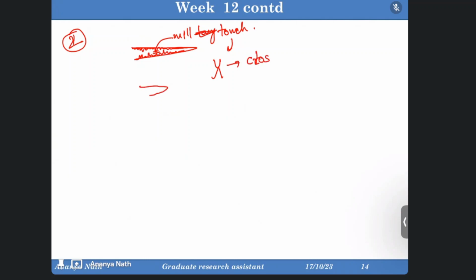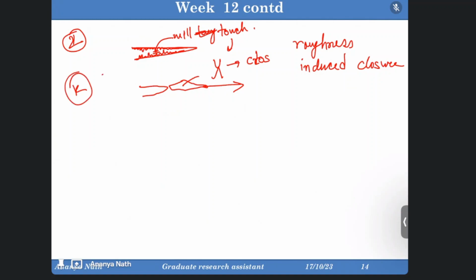So there will be two portions in the crack now, like this. There can be some void, or this void can again propagate and form a crack. So these things can happen, which is known as the crack closure. So crack closure is due to the roughness which is present over the crack. So it is also known as the roughness induced closure. So if there is a bulk material inside which there can be a lot of cracks present due to the application of external load at the time of fatigue testing or any other type of testing, if there is a crack in the interface, if there is a crack in the matrix, whatever it is, this crack closure can happen depending upon the K value, which is the stress intensity.